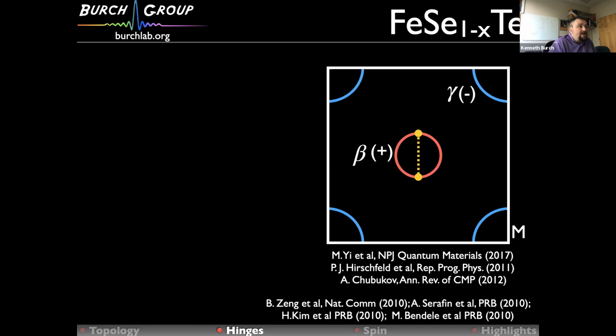Okay, and it was known, I think, very early on, right, that if the pairing was all intraband pairing, then you would probably just have a multiband S-wave superconductor. But that if you had interband pairing, because you have this pairing between electrons and holes, that you would have what's called an S plus minus, which is to say that you have a change in the sign of the order parameter as you go from gamma to M.